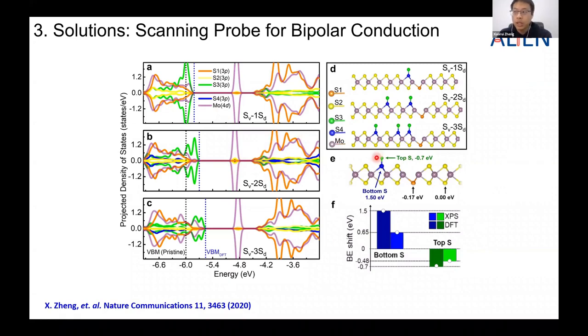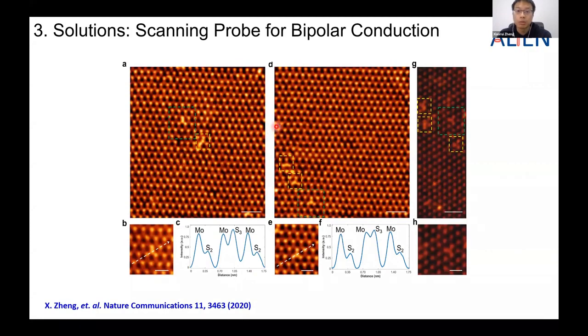Okay, so far we have used the Raman spectrometer, XPS and DFT, and after that we use STM to observe whether there's this kind of sulfur-sulfur bond in the atomic matrix. And as you can see here, we can see some contrast in the lattice, and we identify this contrast as the S3 contrast. This is the evidence that the S-S bond can be observed in the STM image. And by comparing different images at different locations, the concentration of this sulfur-sulfur bond is determined to be around 3% to 4%.